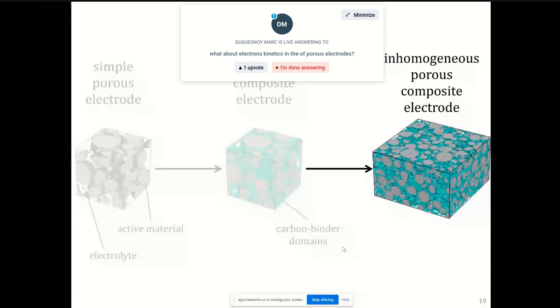So, to speak in more conventional parlance, you can do electrodes like 95, 2.5, 2.5. So 95% active material, 2.5% carbon, 2.5% binder, and about 25% porosity. And as long as you're within the 50 micron, 60 micron range, you wouldn't run into limitations from the electronic conduction.